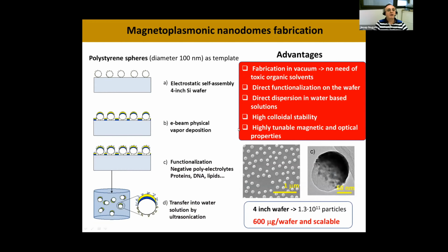So how do we go about this? First we get commercial polystyrene spheres. We usually use 100 nanometers, but you can use other sizes. And then we self-assemble them on a silicon wafer. And then we evaporate the iron and the gold layers using electron beam evaporation. And then if needed, we can functionalize them while they are still on the wafer. And then using ultrasonication, we can transfer them to water.